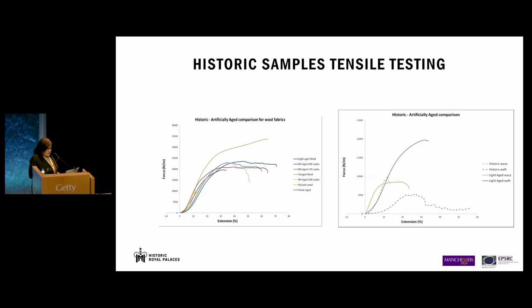As part of Philippa's project, we had the opportunity for the first time to perform tensile testing on 10 historic samples. So the figure on the left shows the comparison of historic and light aging fabric, which suggests that the historic samples, you can see there the tiny line, were much weaker than the artificially aged ones. The graph on the right shows the tensile testing results of the aged replica samples in full line and the historic tapestry fragments, the dotted lines, in both weft and warp directions, indicating that the weft on the historic samples was considerably weaker following long-standing degradation.